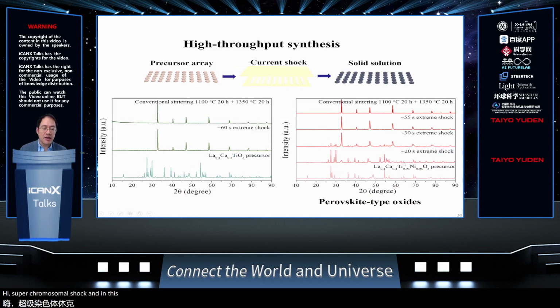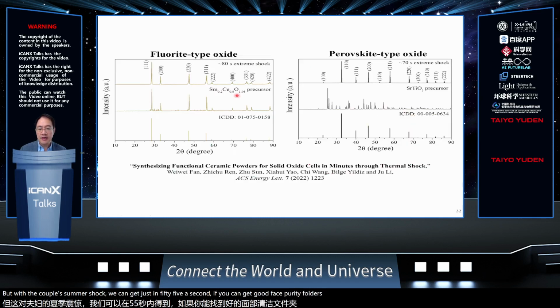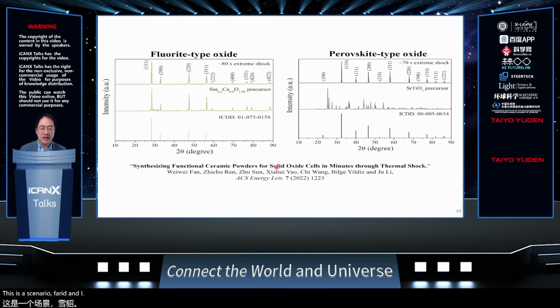And in this plot, I'm showing that you can use this approach, in addition to making multi-metallic particles, to make oxides. This is a lanthanum calcium titanium nickel perovskite material, and traditionally you need 20 hours in solid state synthesis to get phase purity. But with the carbothermal shock, in just 55 seconds we can get good phase purity powders. This is a samarium cerate, and recently, in collaboration with Professor Bilge Yildiz, we have shown that you can produce the raw material for solid ceramic fuel cells and electrolyzers using this approach in minutes.